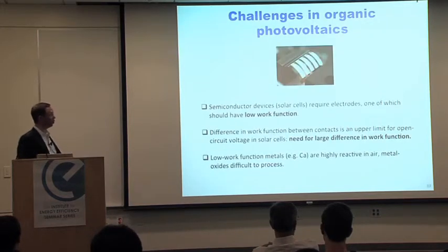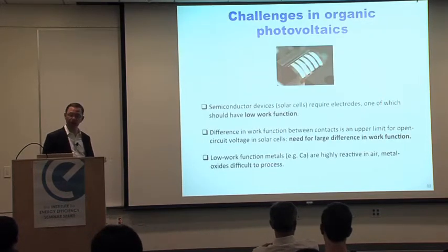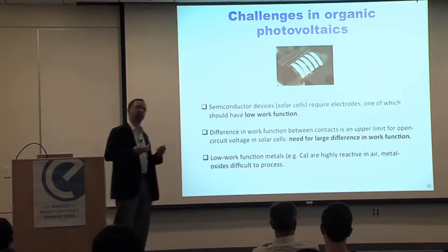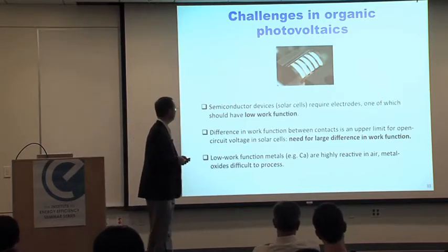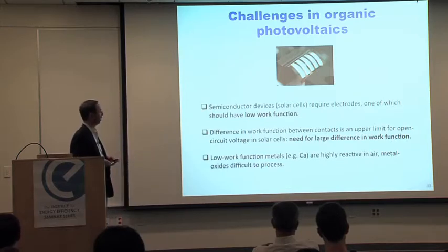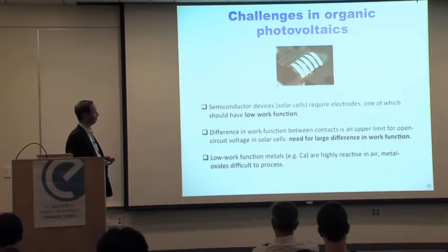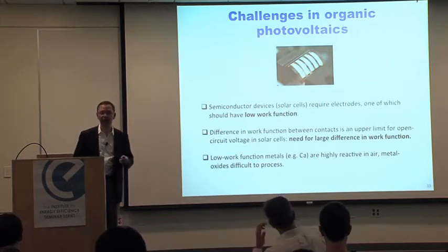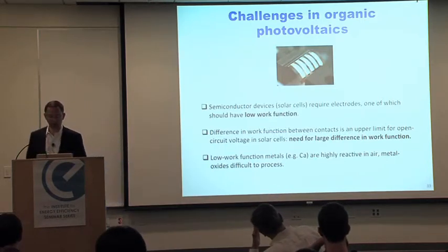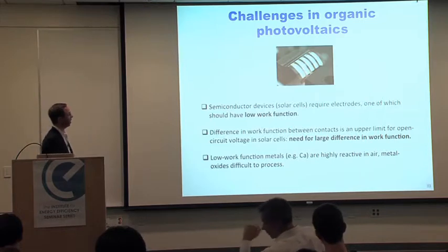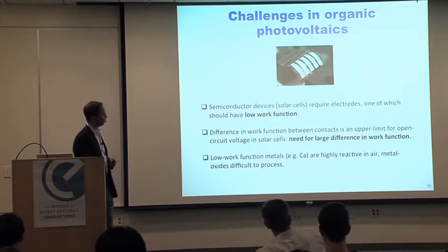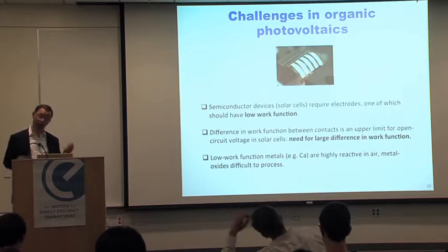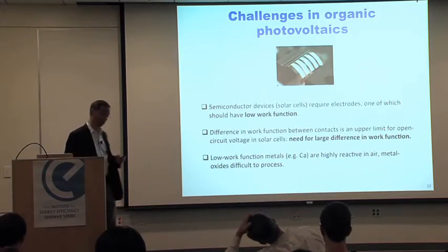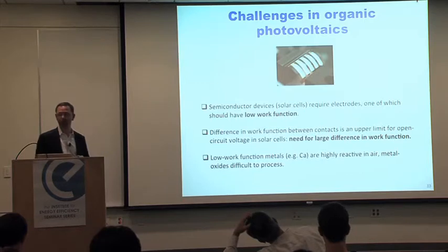Okay? And so you see these diagrams, and because of the need for an asymmetry in a solar cell, you need both high and low work function electrodes. And the challenge with a low work function electrode, as I mentioned earlier in the context of OLEDs, is that materials such as calcium or lithium fluoride and so on are highly reactive, and so that limits the stability of these materials unless you use a very expensive encapsulation technology, which we can't afford, because the game in solar is really you want to lower the cost as much as possible.